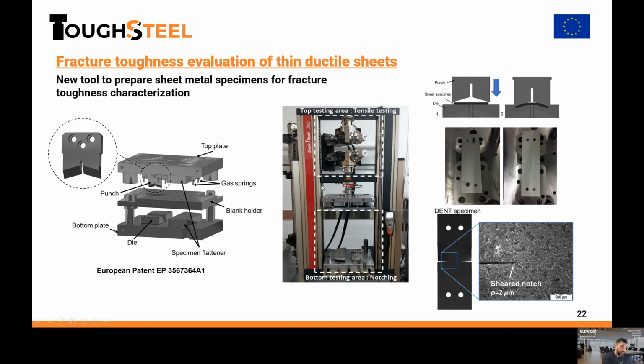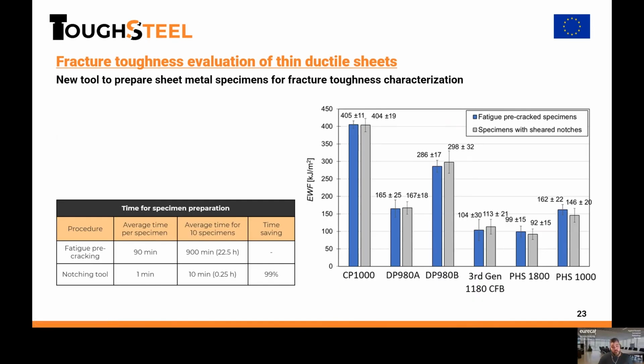Of course, this tool has been validated for different advanced high-strength steels. Again, here on the right we have some results with specimens obtained with fatigue pre-cracks and with specimens obtained with these sheared notches, for a wide range of advanced high-strength steels. We're also still validating the results in different aluminum alloys, stainless steels and so on. But what we found is that this is a very interesting tool to obtain equivalent, or let's say reliable, fracture toughness values in a very short time.